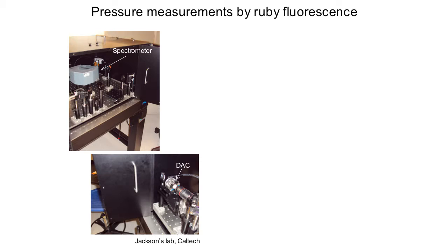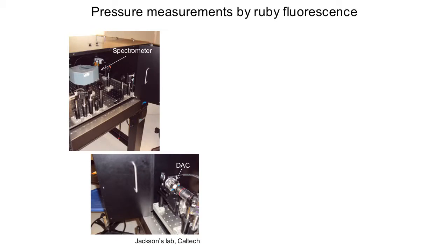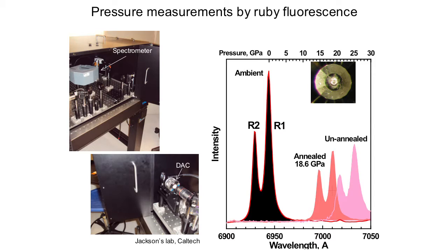And then one has to ask, how do we know what pressure or depth this mineral is experiencing? So in some cases, we use a ruby that's placed right next to the sample, and the chromium inside of the ruby gets excited by a laser, and we measure that fluorescence. As we squeeze the cell, the volume around that ruby decreases, and the resulting signal from the ruby, as it's fluorescing, increases in wavelength in response to that volume change.